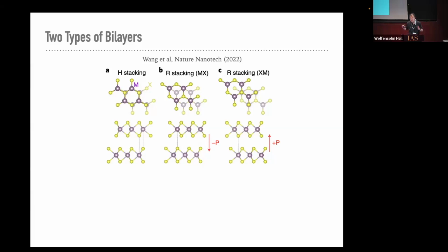Now, what's the big deal here? So the big deal is that, remember that in my TMD system, I have the so-called spin valley coupling, right? So each valley has a specific spin component. Now, this is a top layer. This is, oh, I should have rotated this. This is spin down. Okay, so it's a good thing I have a different color. So basically now this is the top layer, this is the bottom layer, because you have rotated by 180 degrees. So therefore, for the same valley, the spin orientations are opposite. So then in this case, the interlayer tunneling is actually forbidden.